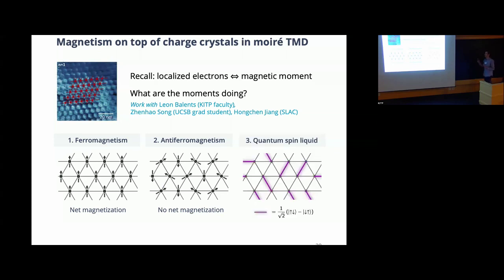This is now something that I cannot demonstrate to you anymore in terms of arrows because it's an extremely non-trivial quantum state. So the state that we can roughly think about here is that on any given site we form a superposition state, so this weird quantum mechanical mix basically between two sites where they are in a simultaneous state of up and down and vice versa, right? Up, down, minus down, up here on this bond. And now on top of this, I take a superposition of all these different coverings. It's an extremely non-trivial state which doesn't have any classical analog, which is extremely exciting for us.